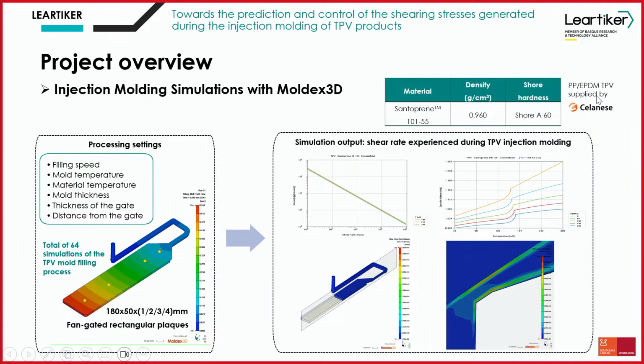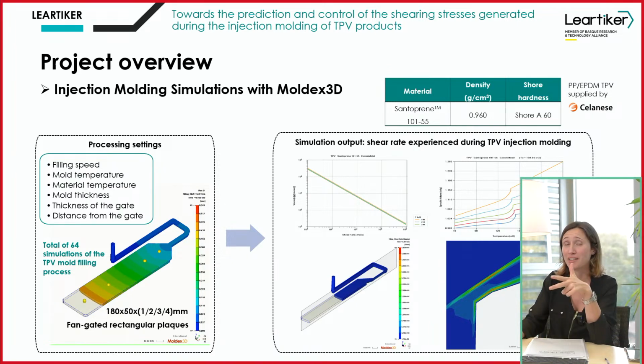So in this case, we are using an EPDM TPV that was supplied by Celanese. It has a Shore A60 hardness, which is the range of hardness that we have in anti-vibration components that are used in the automotive sector. And in this case, we analyzed different processing parameters. For example, on the one hand, filling speed, mold temperature, material temperatures. So parameters that we can check and control during the injection molding, but not only process parameters. We are also analyzing geometrical parameters.